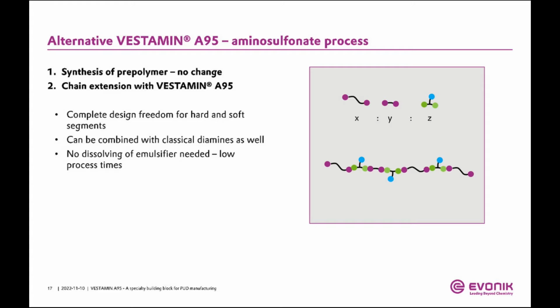You can use the A95 as chain extender alone. You can also combine it with the EDA, the classical diamines, if you choose to use less A95. This is an option. So you have basically way more design freedom because you need less of this molecule and you can combine it with long chains, short chains, prepolymers. You can combine it with other amines for chain extension. Everything is up to you. And the last part, as I said also on the last slide, no dissolving is needed. So other than the DMPA, we have a directly liquid to start from in your synthesis.